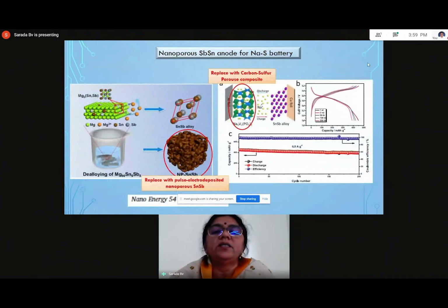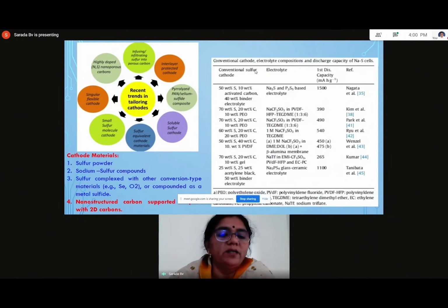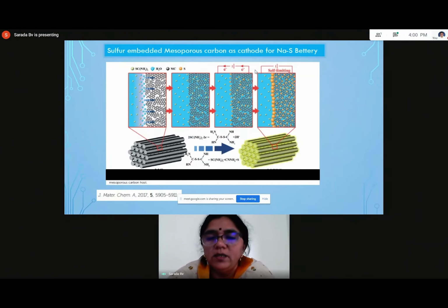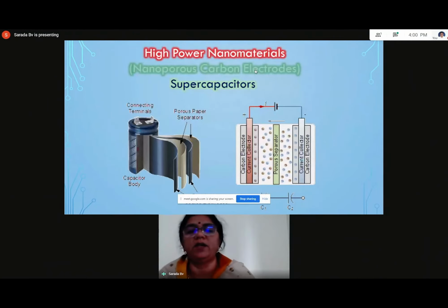And so here you can see this is the anode that can be prepared. This is the futuristic battery. You can make a porous tin antimony structure and introduce sodium into this to be used as anode, and also you can use mesoporous carbon and microporous carbon structures to introduce sufficient loading of sulfur into these carbon structures in order to get the best performance of the sodium sulfur batteries. And we have already started working on the nanostructured carbon to introduce the sulfur into these structures.